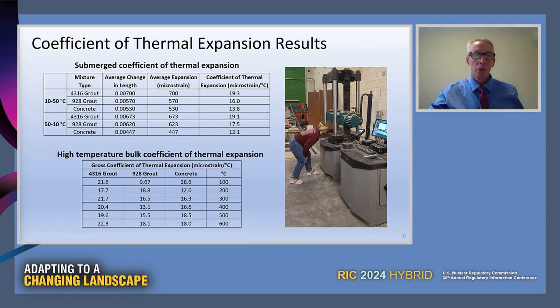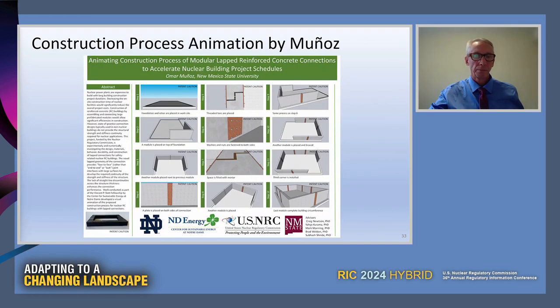So out of the work that we've done so far, in the second column of this top table, you'll see the two grouts, the 4316 grout, the 928 grout, and the concrete. And what we're doing is looking at coefficients of thermal expansion for these materials. So when you go to the right column, you'll see the coefficient of thermal expansion values. And the grouts have a little bit higher coefficient of thermal expansion than the concrete, but everything is reasonably close. So things are looking at least a little promising there. Next slide, please.